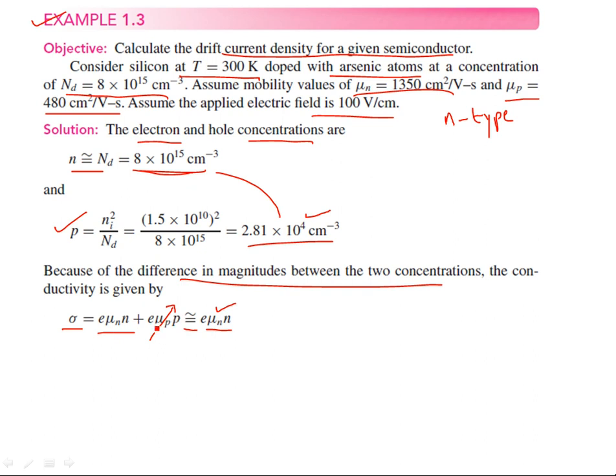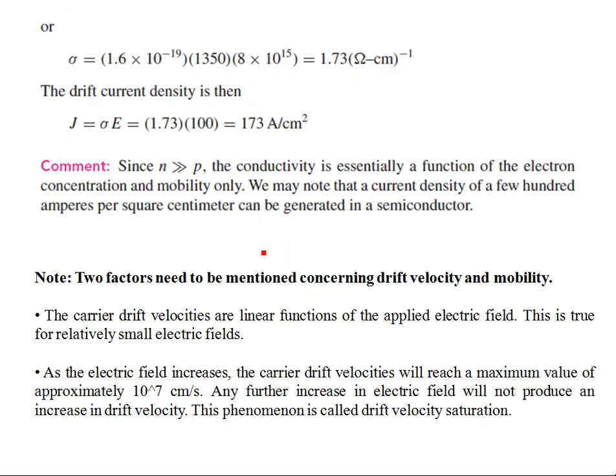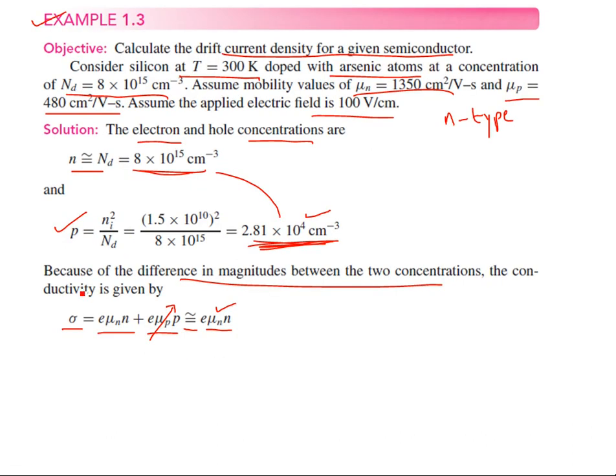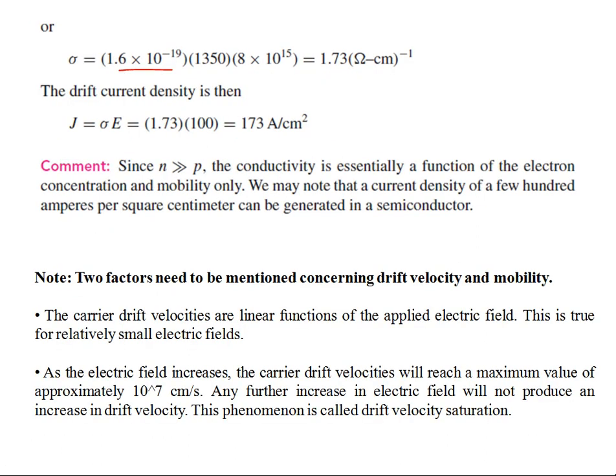Okay, so we don't need to even consider the holes, because of the very small concentration of holes in the N-type material. If you just plug the values in to find the conductivity of the material, the mobility of the electrons, the charge, and the concentration, which is given as such, this gives the conductivity as 1.73 ohm centimeter inverse, and the drift current density is then evaluated from the linear relationship from the given electric field.